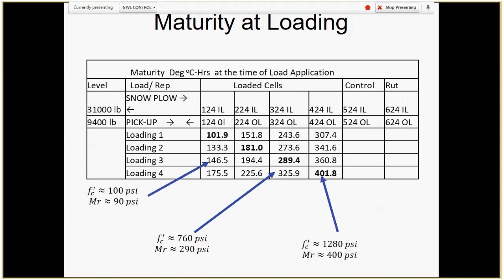and when the cell 424 was loaded, the compressive strength was still quite low, but the flexural strength was quite significant, and according to ACPA criteria, this pavement should not fail. And basically, it's interesting, none of them failed, but I still can't understand why 124 didn't fail. It's important to point out that the first loadings were made at the maturity level for which we even don't have reliable tensile and compressive strength.